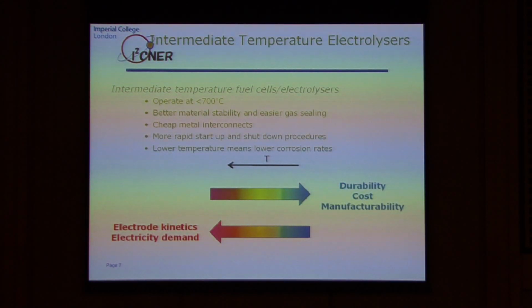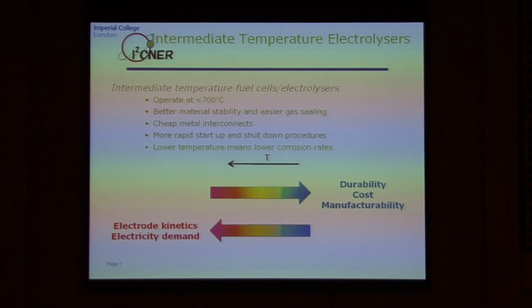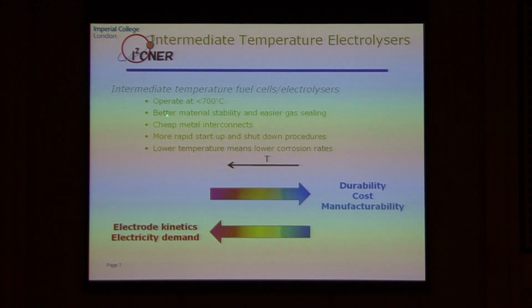So we need strategies to get rid of these bottlenecks to development of high-temperature cells. The way forward is really to move to intermediate temperatures - as defined by the high-temperature electrochemistry community, so some of you might not find less than 700 degrees centigrade an intermediate temperature. In this range we have better material stability, easier gas sealing. Down at 600 to 500, we can use stainless steel and compression gaskets to seal, cheap metal interconnects, more rapid startup and shutdown, and good stability during thermal cycling.